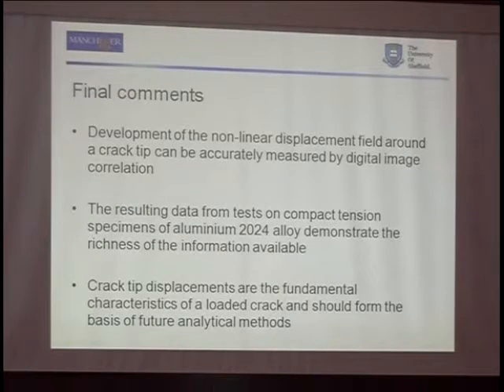So, just some final comments. The development of the nonlinear displacement field around the crack tip can be accurately measured with DIC, especially if you've got the right optics. The resulting data from the tests in 2024 demonstrates the amount of information that's available, and we've probably not even scratched the surface in terms of analysing what we've got. And we believe that crack tip displacement fields are fundamental to the characteristics of the loaded crack.